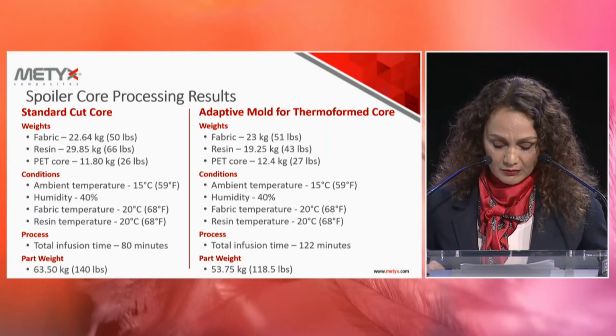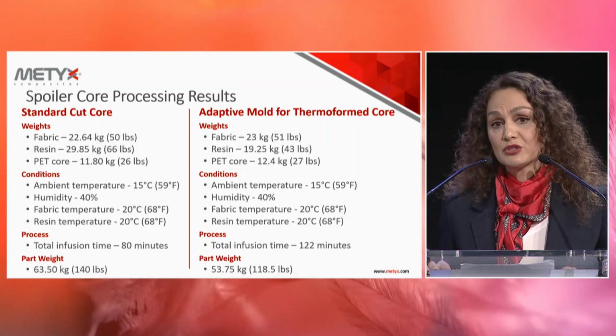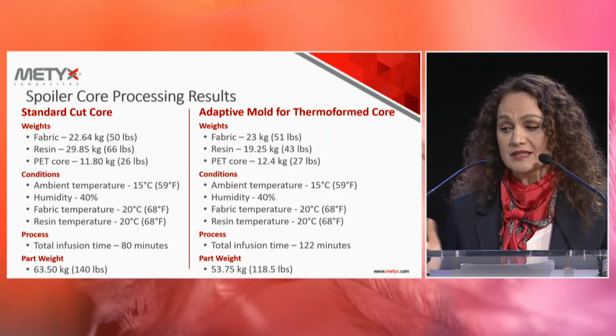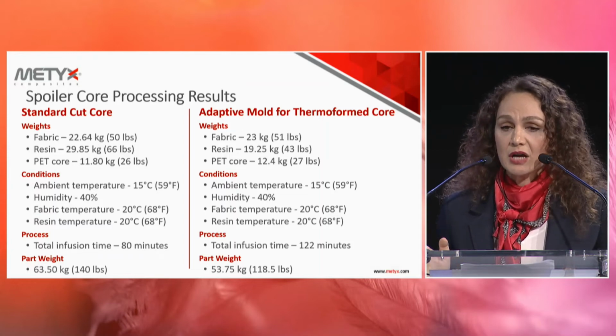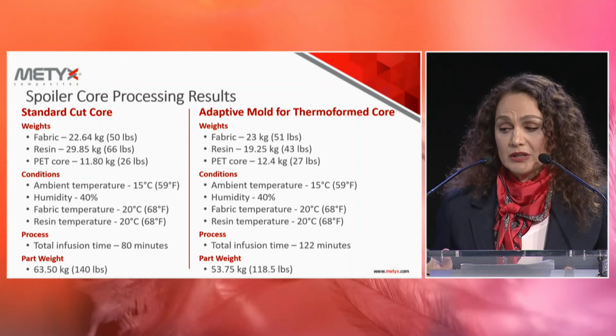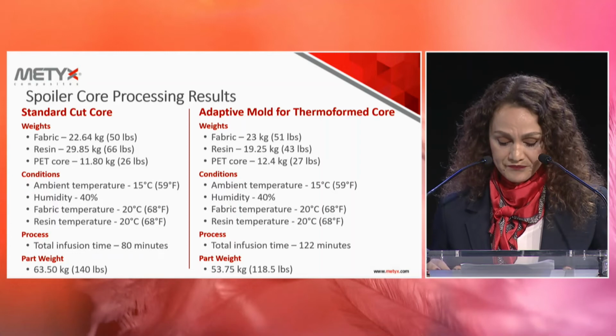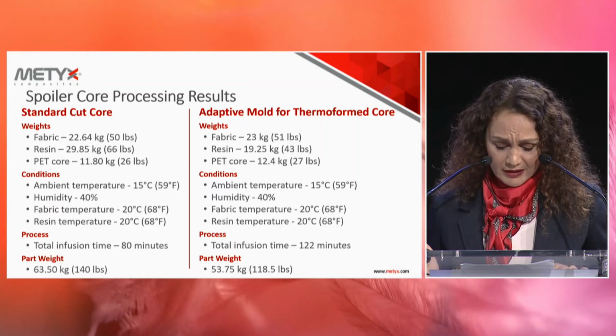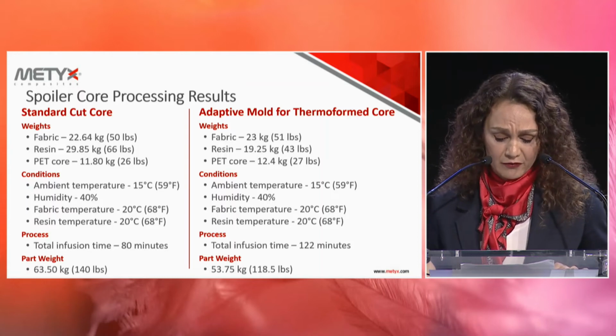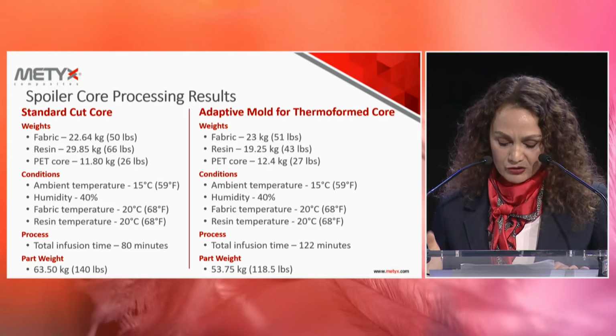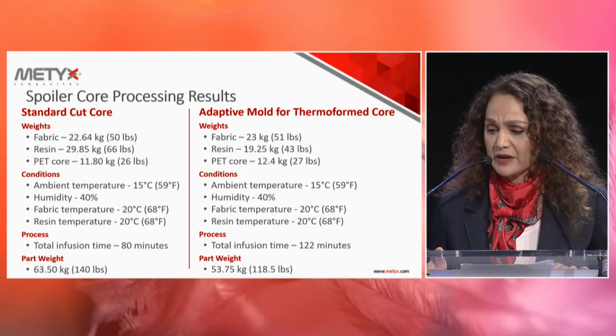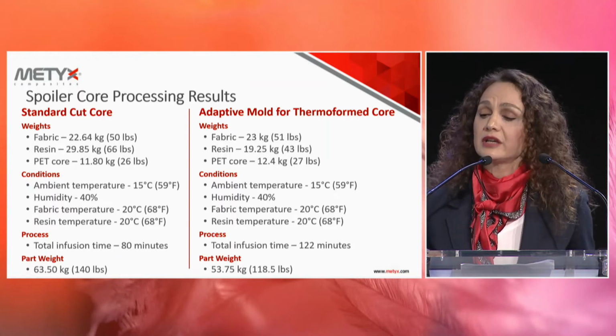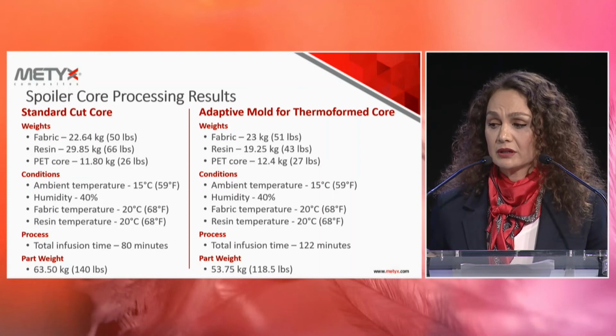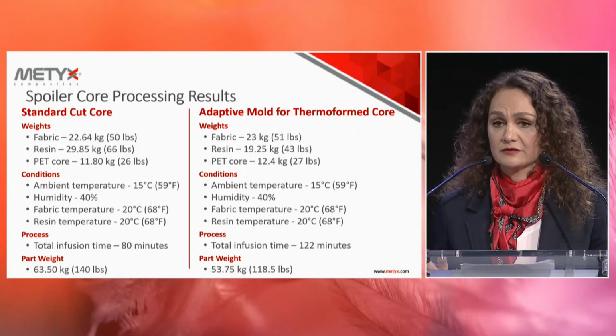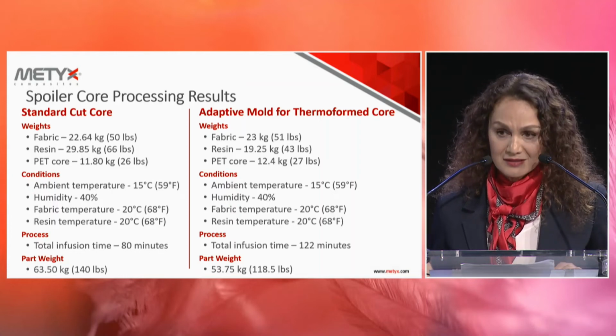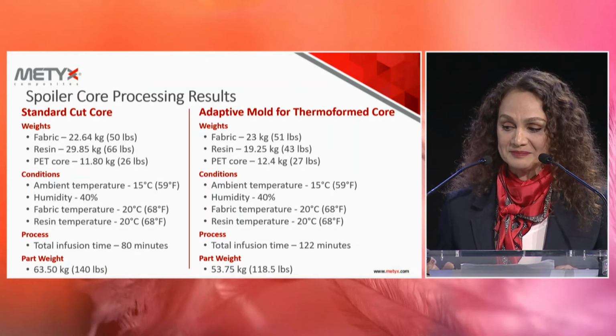Actually, we made no move to reduce the infusion time or increase the processing time. We were just focusing on the resin consumption and weight savings, building material cost, to reduce the cost. So there is obviously a balancing act to understand resin weight, part weight versus process time. But we did not concentrate on that now. If you look at the part weight here, for the standard core it is 63.5 kg, and for the adaptive mold thermoformed core it is 53 kg, which is very low. It's an enormous, tremendous part saving.